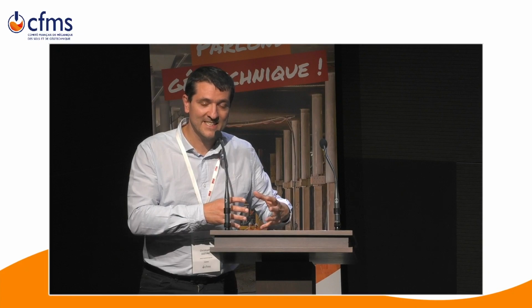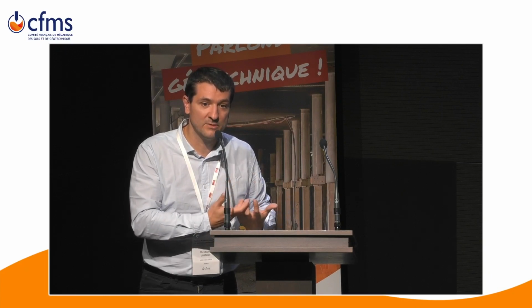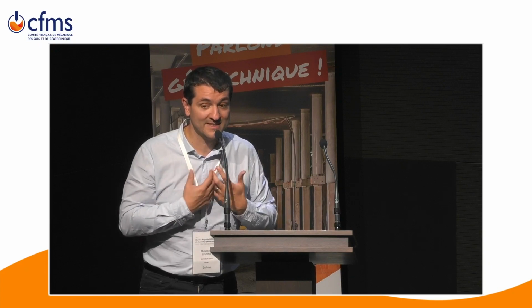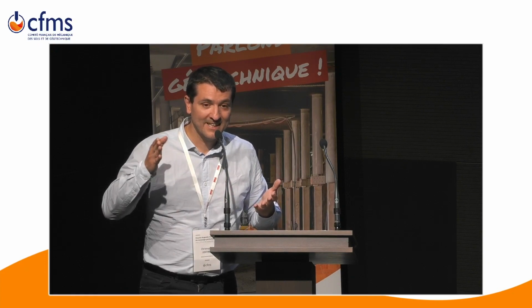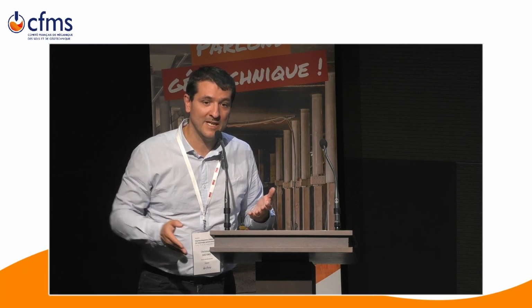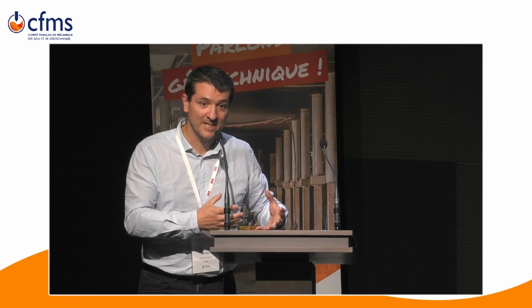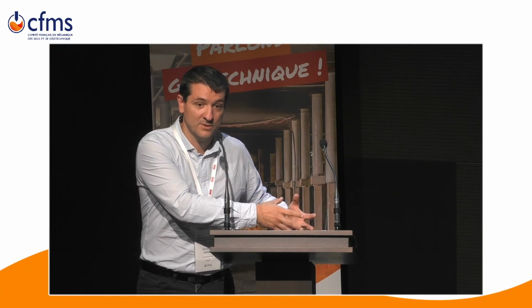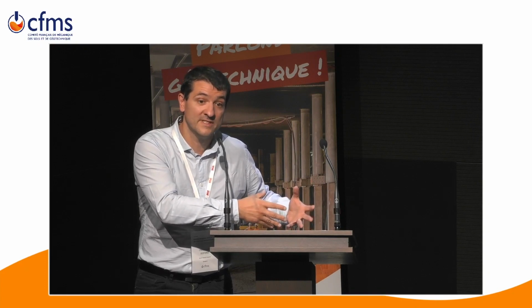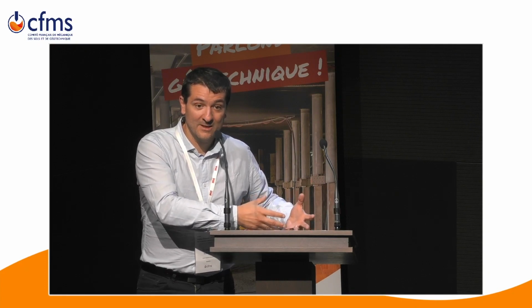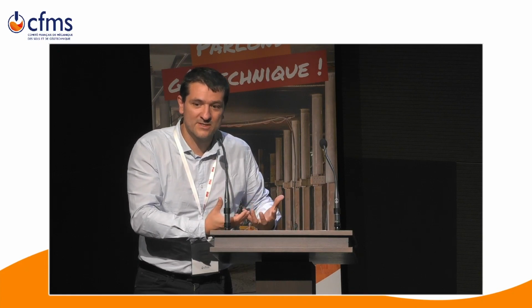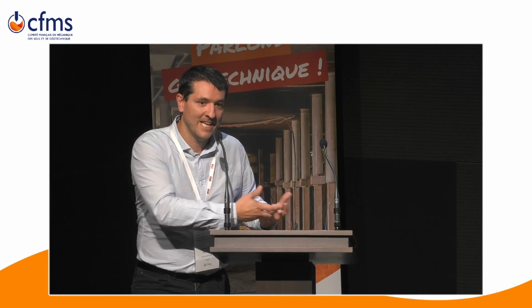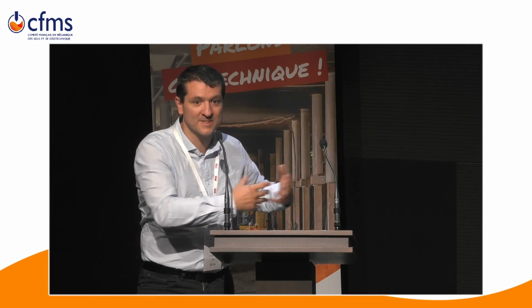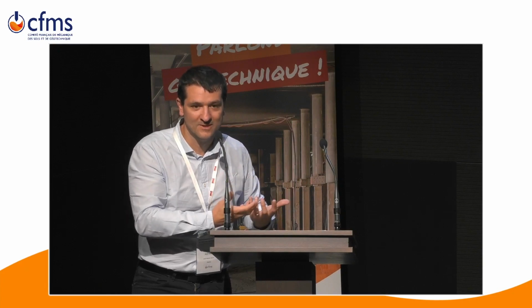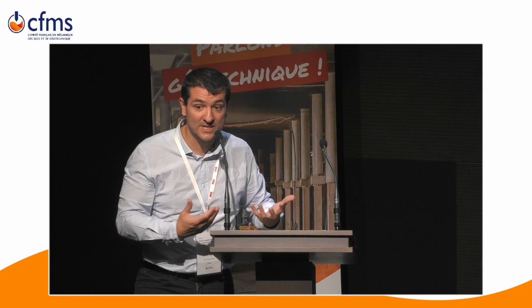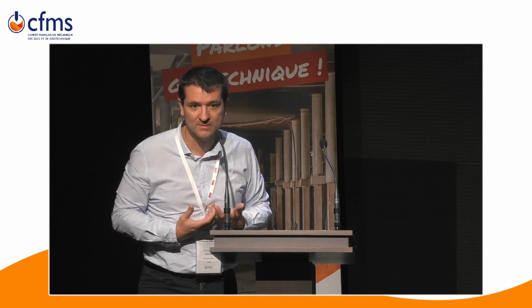exists for concrete is that strength is part of the durability requirement. So most of the time what I see on piles and D-walls is that even if you need 25 or 30 MPa for the calculation of the structure, depending on the exposure class and the aggressivity of the soil, you might have to design up to a C40, and you are not using all this strength for the calculation, but for the durability. That's the main interest of the performance-based approach, because now we have a way maybe to avoid over-designing a concrete in terms of strength, when in reality for the design we are not using these strengths. So that's a way.